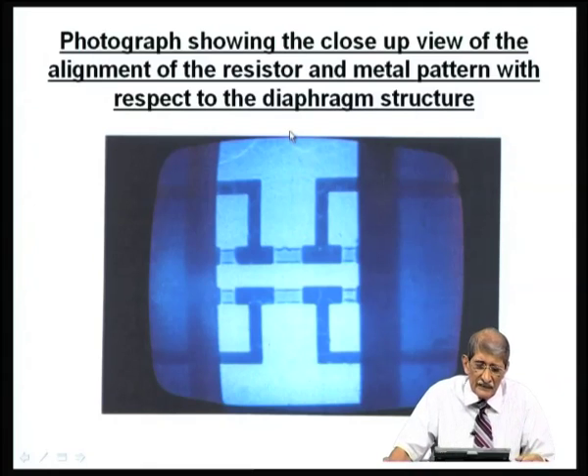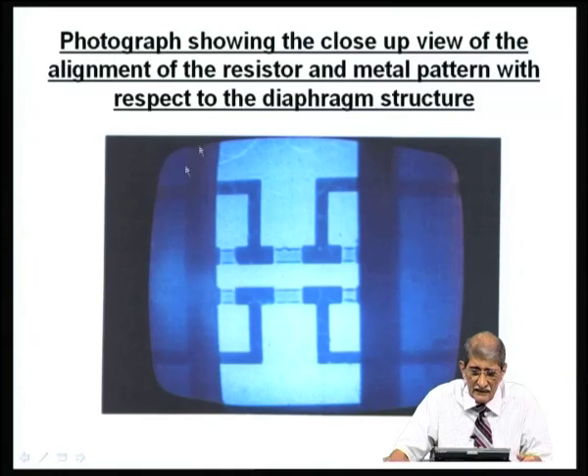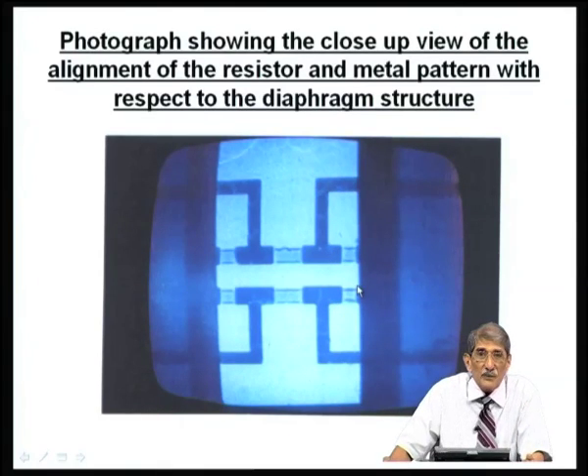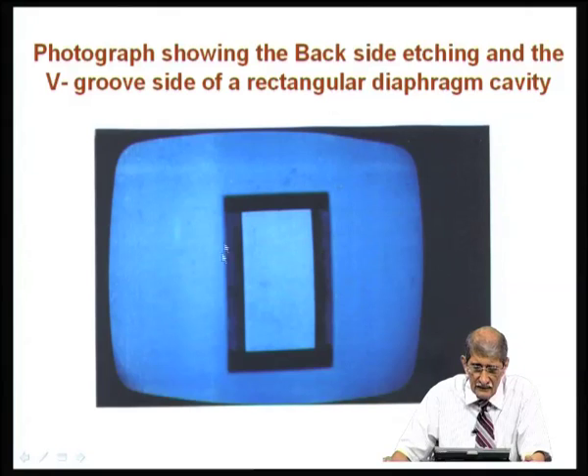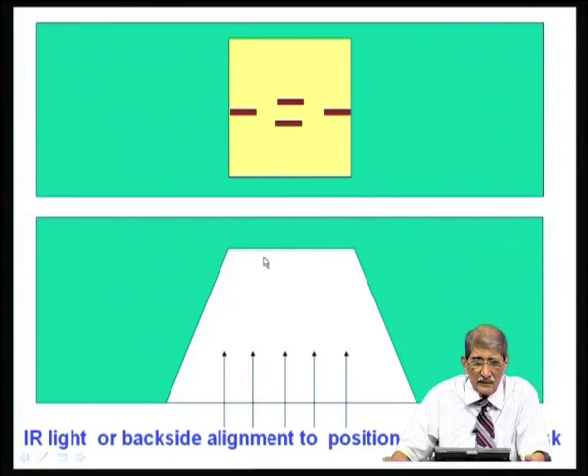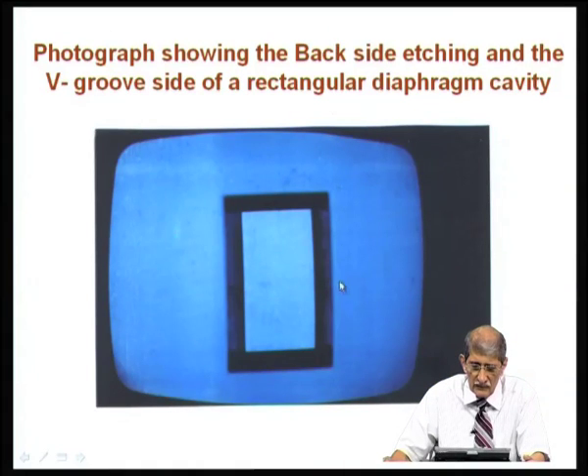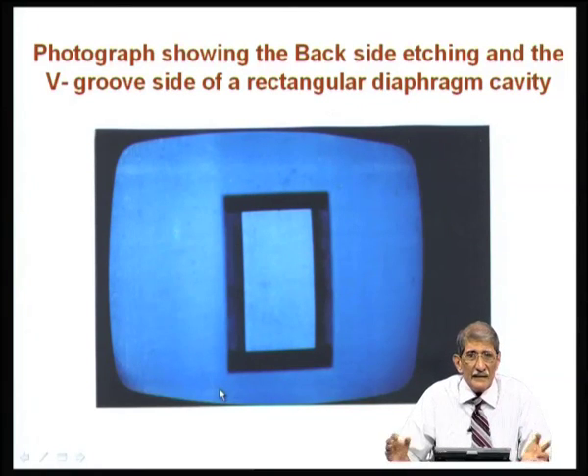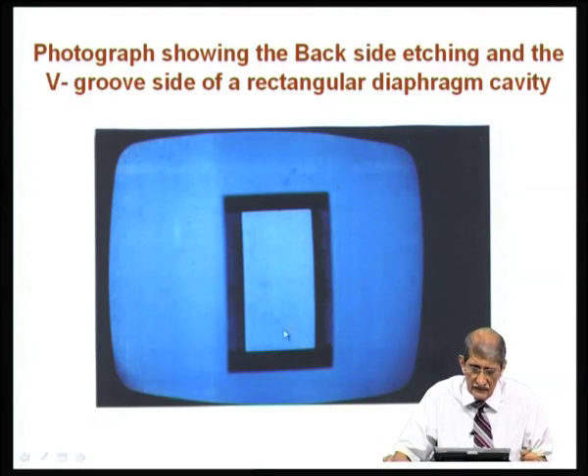Okay. Now, when you see from the IR aligner, this is what you will see, this is the membrane, these are the resistors which you can see. So, you can precisely see where to locate these resistors. I have just taken this photograph from the video camera. And if you look at the back side of this membrane, if you look from that side, not IR, through a microscope, that is how it will look. This is the edge where we etched, this is the sloping side, and because it is sloping, when you look at it under a microscope, this portion looks dark because light will not be reflected there. So, when the light is not reflected, it will look dark. You see this is the bottom of the etched portion, that is the membrane looking from the back side, this is the top of the wafer on the back side.